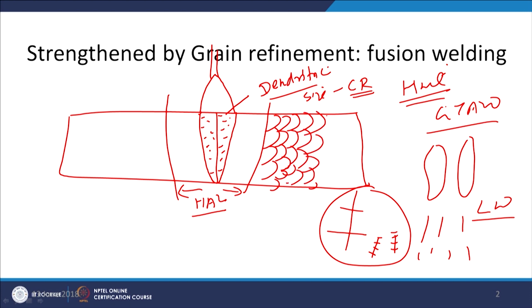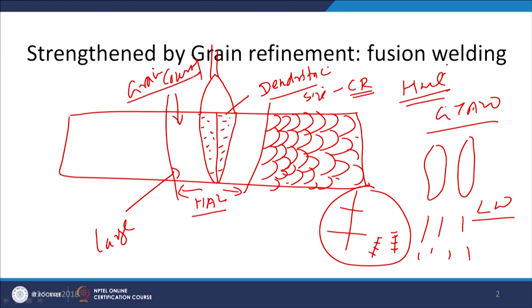and we know all kinds of metal systems, when they are exposed to high temperature, tend to attain a larger grain size, so that the associated surface energy can be reduced. So, the zone which is experiencing the effect of heat of the fusion welding will be subjected to grain coarsening, because through the grain coarsening the surface energy associated with that particular metal will be reduced. So, all the grains tend to get coarsened, so that the associated energy can be reduced through the reduction in the grain boundary area, while when the grain size is fine, the grain boundary is more, and the associated surface energy is more.